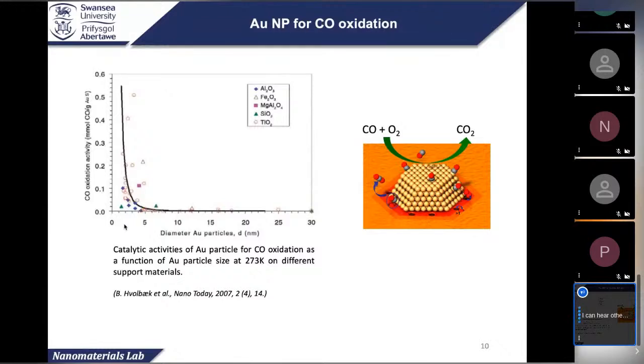The problem during the reaction is the sintering. The small gold particles may sinter with each other and become bigger. Then basically you just lose the activity. They are not active anymore. You can't reduce the size because it's not reversible.